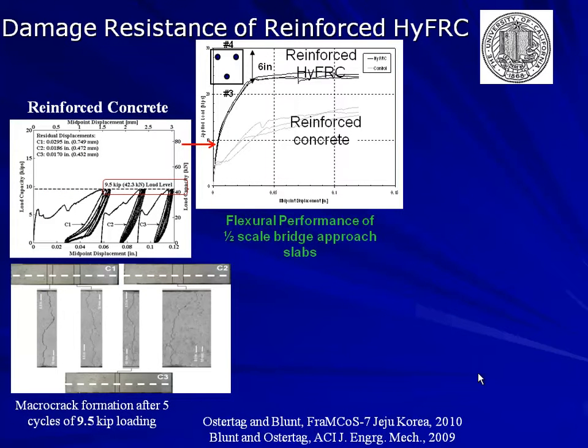Now in regards to cracking. Talking about damage, here we said, what will happen if we load and cycle the specimen at that load level? This is a typical surface load of these bridge approach slabs. What you see here are 3 specimens. I just separated them so you can see them easier. These are 3 specimens of your reinforced concrete, and what you see very clearly are these very dominant cracks. You form very dominant cracks in that specimen.